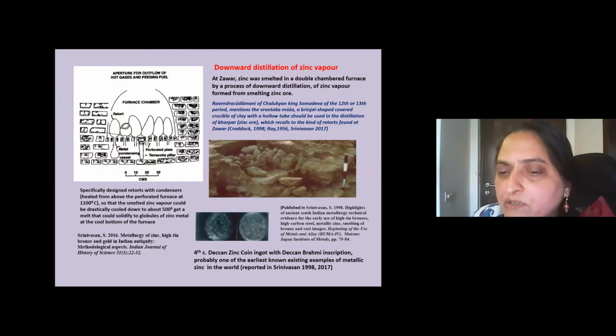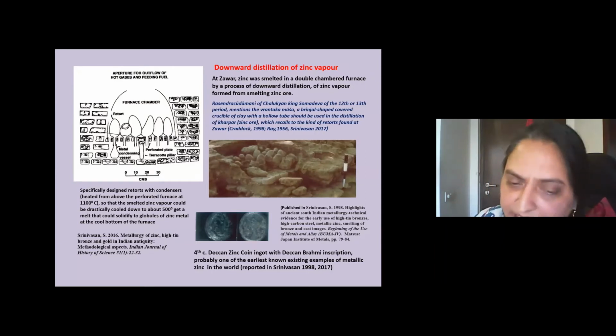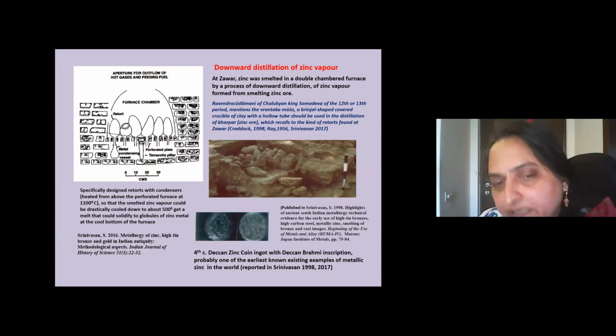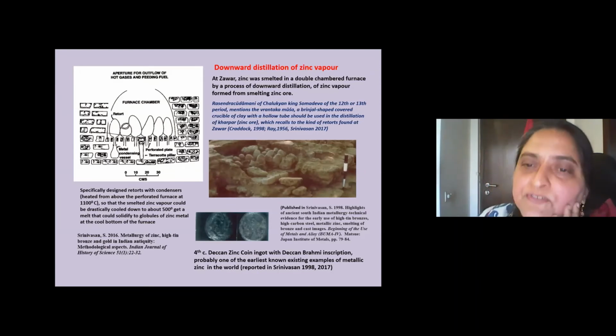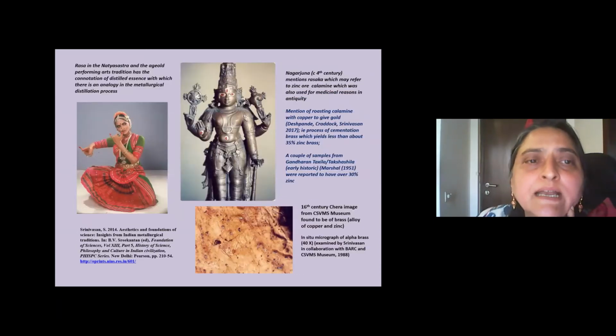And what you're actually looking at here at the bottom, you see some of the furnace remains, is also a Deccan zinc coin, which I was able to also study, which had a date of about the 4th century because it had this Deccan Brahmi inscription, and I'll come to it a bit more again in terms of the lead isotope analysis and such like. And this is perhaps one of the earliest, at least surviving examples of metallic zinc from the Indian subcontinent, perhaps one of the few from anywhere in the world as well. And what's also interesting is that it's like a droplet and the bottom is flat. So you can see that the distilled vapor has then condensed into this sort of globule, which is exactly as you would expect. So this is also another interesting aspect to it.